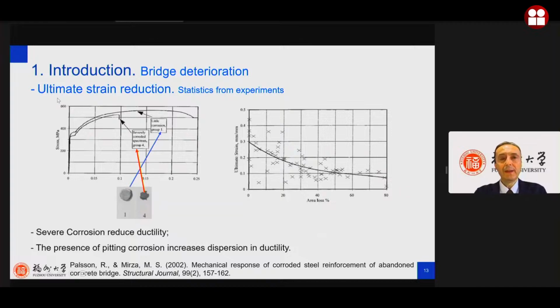I told you regarding the ultimate strain reduction. So it's well known, starting from studies that are already more than 20 years old, that severe corrosion reduces ductility. You can see from these diagrams, this is, for example, a severely corroded specimen, and you can see how the ductility is influenced. But also the presence of localized corrosion, the pitting corrosion, influences the dispersion in the ductility. And this is, of course, very, very important. If you have very dispersed results, of course, you need to consider this aspect.